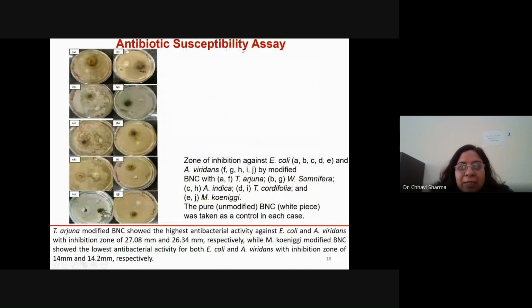Now, the antibiotic susceptibility assay was done for all these modified BNC films. It was found that the activity was highest for T. arjuna, showing a zone of inhibition of about 27 mm, and lowest for the curry leaf, showing a zone of inhibition of about 14 mm.